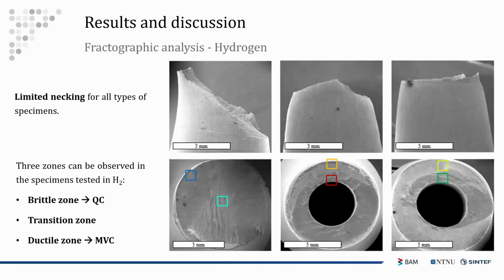Going to the fractographic analysis in hydrogen, we can see, moving from the left-hand side to the right-hand side, the test conducted with a solid specimen, the test conducted with a hollow drilled specimen, so with the higher roughness, and on the right, the hollow specimen in reamed configuration. And we can see for all of them we have a very limited necking, and also 3 different zones. The first one, the closer to hydrogen, is a brittle zone characterized by quasi-cleavage fracture. Then there is a transition zone. And finally, in the part that is far from the exposure to hydrogen, a ductile zone characterized by microvoid coalescence.